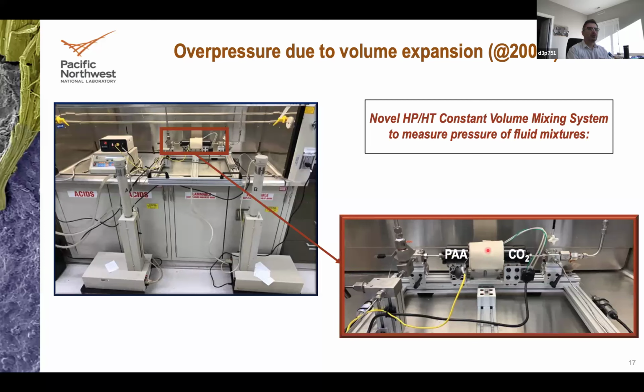When I move the piston, there are 4 plugs, unfortunately I don't have the pictures, 4 plugs of Teflon that will drop if we move the piston in one direction. And we have a bar here that moves the piston, which is not shown here. Those 4 plugs will drop, and then the piston is obviously permeable because the plugs are gone, and the CO2 and PAA will mix. The goal of this is to avoid any dead volume or any change in constant volume. So with this experiment at constant volume, we see if this reaction at any given temperature and pressure generates a volume expansion. It does generate work, stress, okay?